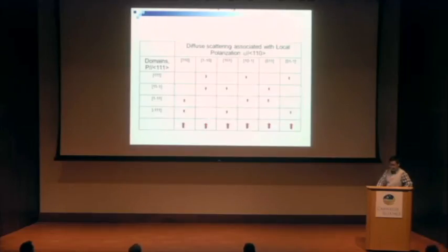And let's also see how the field effect works along the 110 direction. For the 110 field, we prefer 2 domains, along 111 and along 11-1, and don't like the other 2 domains, which are perpendicular to the field.